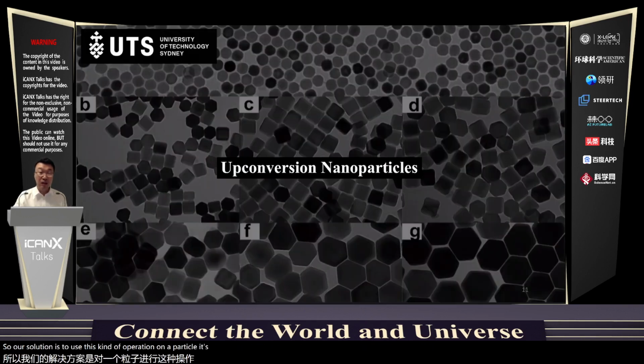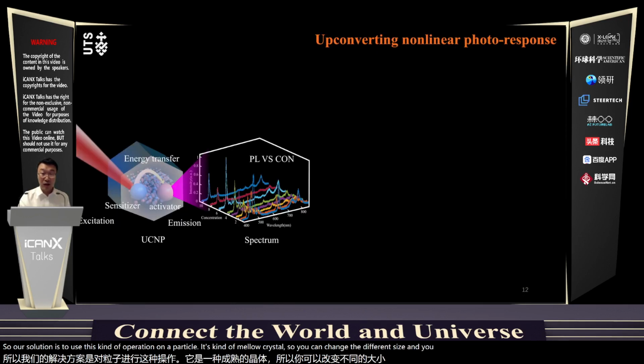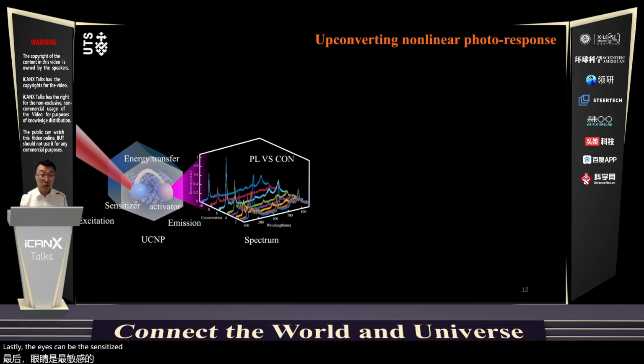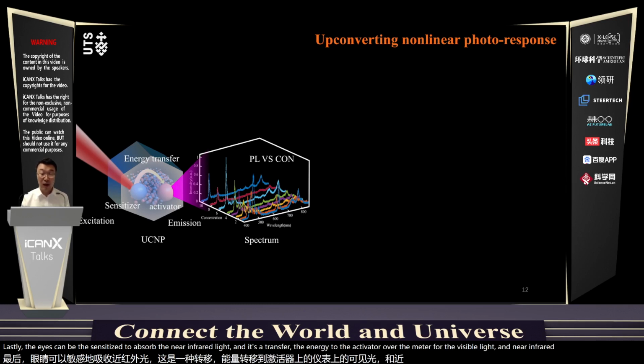It's a kind of nanocrystal, so you can change the size, and you can actually dope rare earth elements inside this single nanocrystal. The lanthanide ions can be the sensitizer to absorb the near infrared light and then transfer the energy to the activator or the emitter for visible light and near infrared light emission.